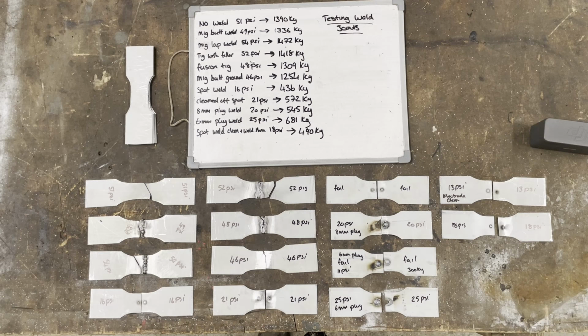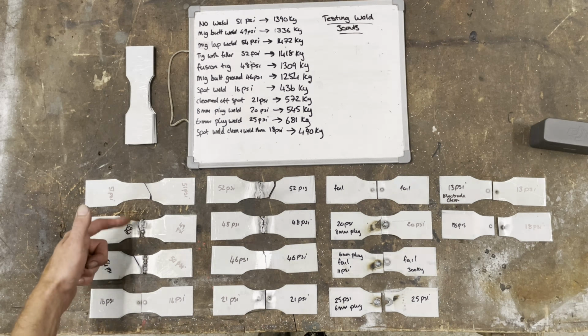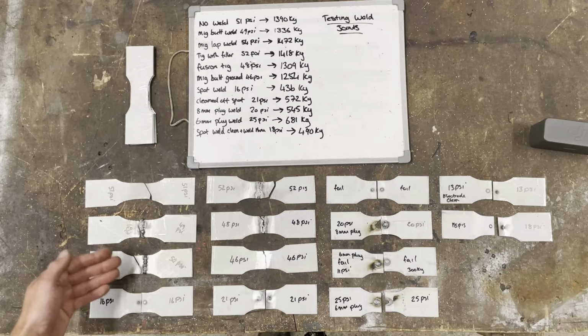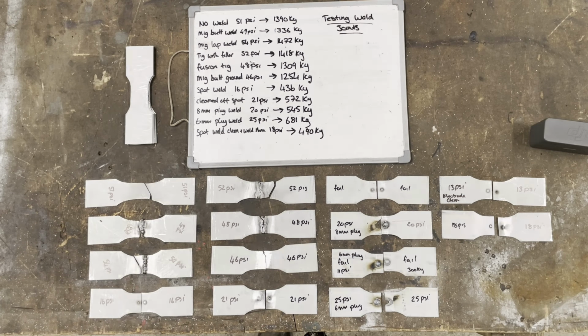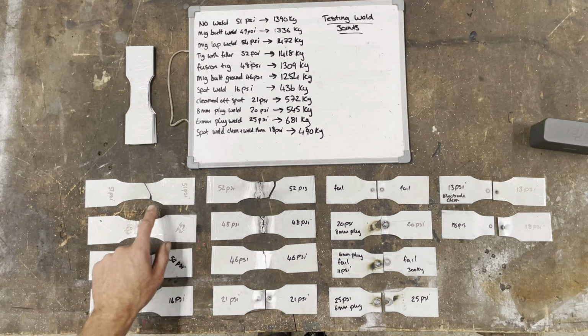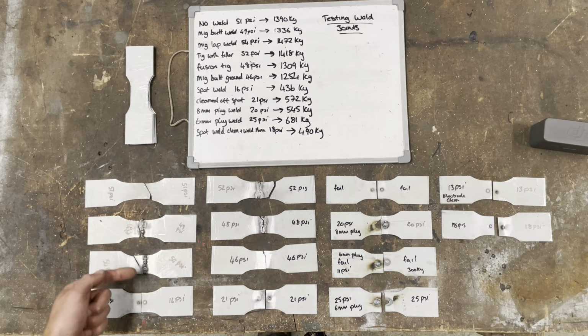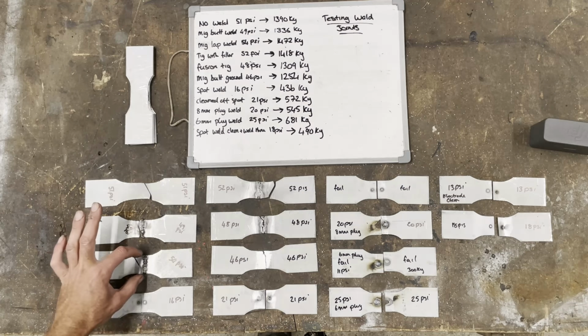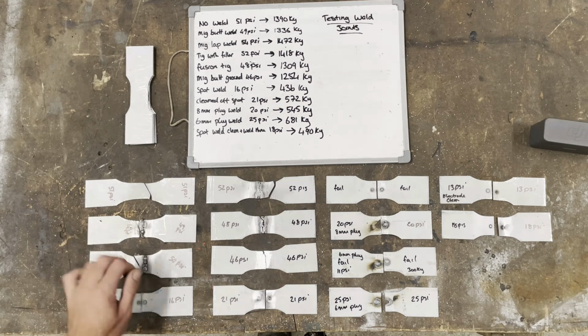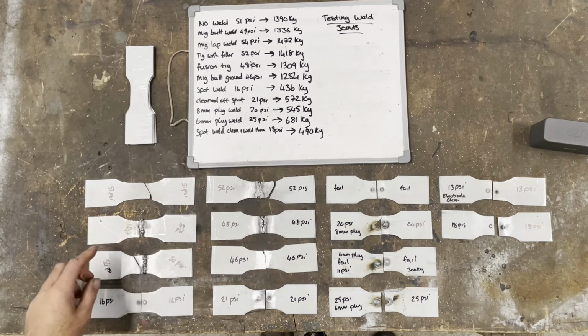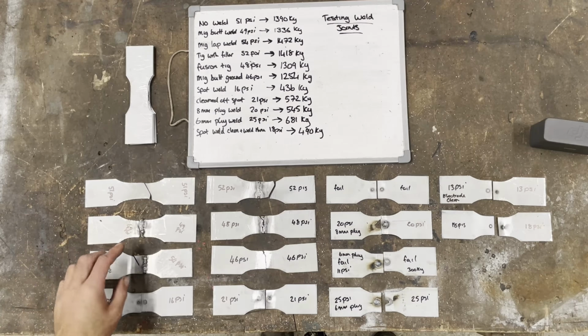What did we learn then? First of all, a lap joint is very slightly stronger than a butt joint, but there really isn't much in it at all. So to say that a lap joint is stronger, not really. If we look at the one with no weld at all, that is 51 psi. The lap joint was 54, and that will be just down to a slight variation in the width. There is certainly no problem with butt welding strength-wise.